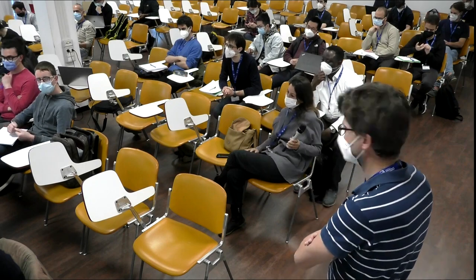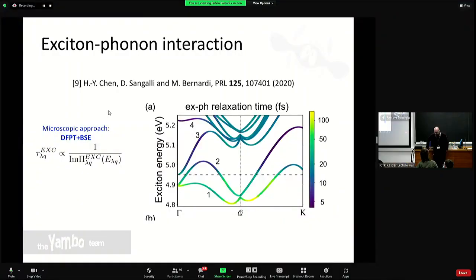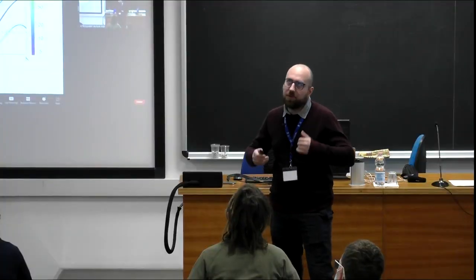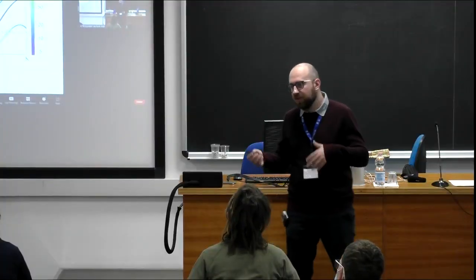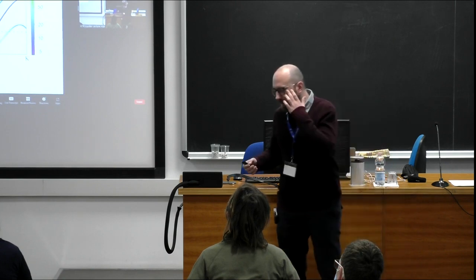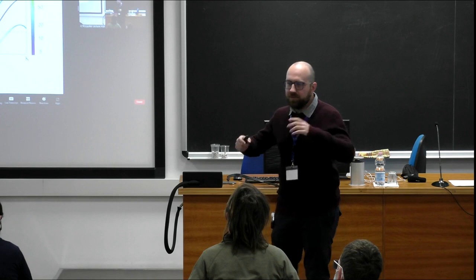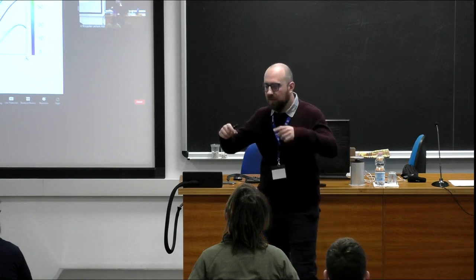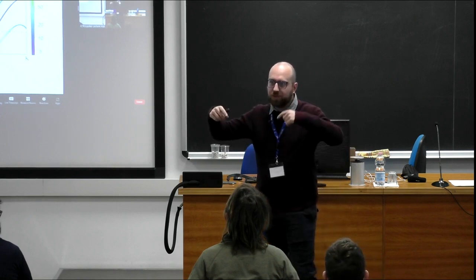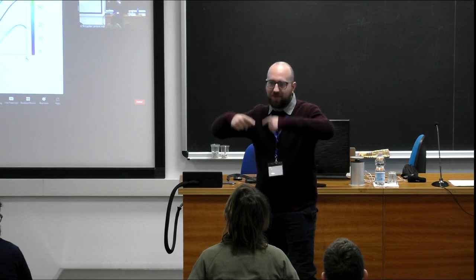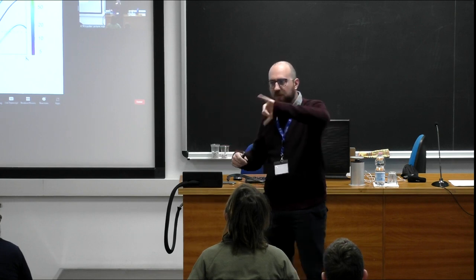So I think in both cases, what it boils down to is that you add the dynamical part of the kernel, which depends to first order on the phonon propagation. So basically, you add, for example, the interaction of the conduction band of the electron with the phonon, of the valence with the phonon, and then the cross interaction between the two.